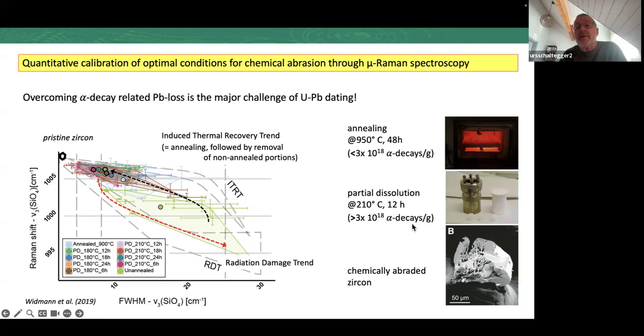By doing this, we hope to get rid of all the domains in the grain which are at the second percolation point, and we are left with a grain which is a skeleton consisting only of repaired domains of the zircons at the first percolation point. And we can actually calibrate this or control this by doing micro-Raman spectroscopy.